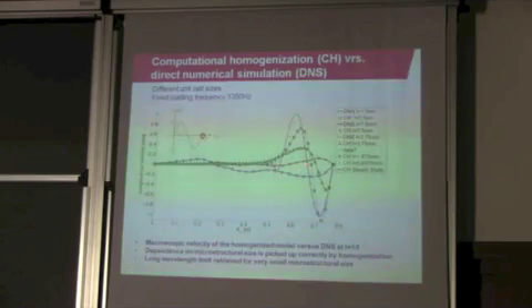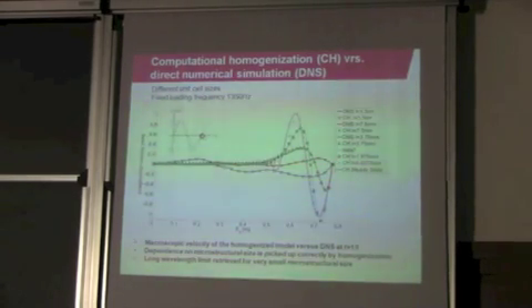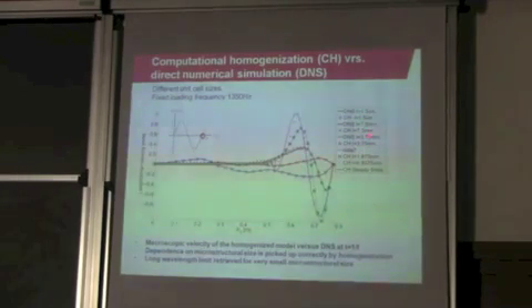So again, the solid lines are the direct numerical simulations and the symbols are computational homogenization. And again, this is longitudinal velocity along the bar. And clearly there is a size effect, so for different sizes of the microstructures and the same excitation frequency, the velocity profile is different, meaning that the material is indeed sensitive to the size of the microstructure.